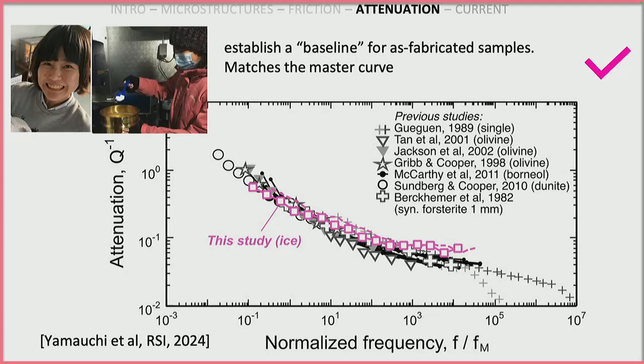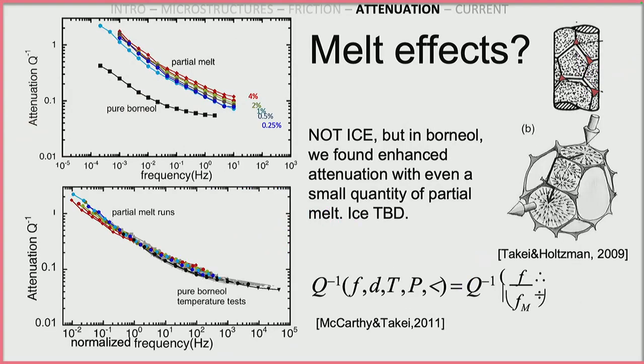We got Priestley Glacier samples, natural samples, that have a really strong fabric, and they had a quite different response that doesn't scale to this, which tells you there are more mechanisms when you have a fabric. There are more mechanisms of generating heat beyond just the little grain boundary processes. Now, I promised you we'd talk about melt. Our goal is to also look at melt in samples with this apparatus. We haven't done that yet.